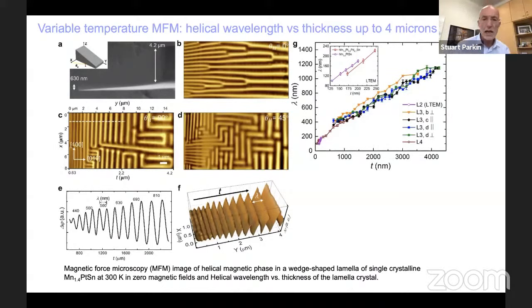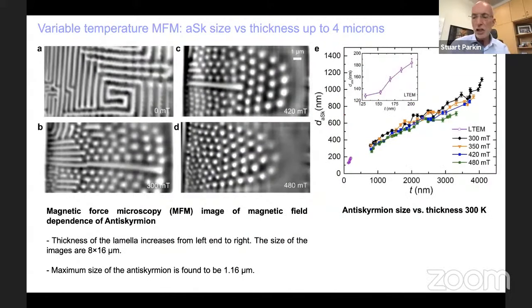So this is a beautiful result. And similarly, now by changing the magnetic field, instead of the helical structure, we can stabilize the antiskyrmions. And in the magnetic force microscope, the antiskyrmions look like single blobs or single circular entities, as shown here. So on the top left, you can see the helical structure, magnetization rotating from up to down in a sinusoidal fashion. And then here, in the other regions, you can see the antiskyrmions over the whole wedge. The wedge thickness here is varying from 0 to 4 microns. And you can see the antiskyrmions are varying from small on the left to big on the right as we change the thickness. So this is amazing. And the maximum size of these antiskyrmions we found so far is about 1 micron.